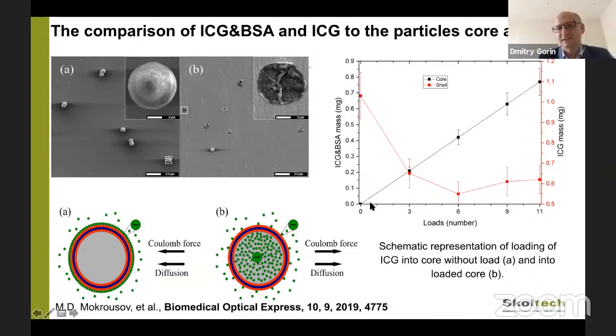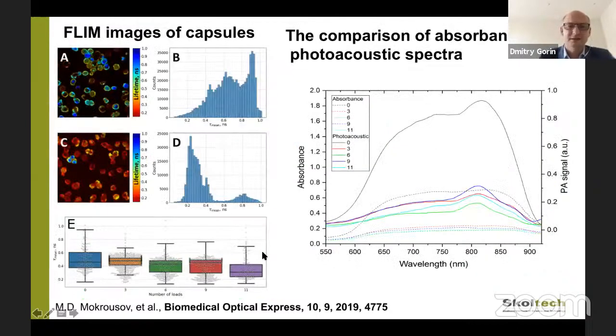It looks like this. If we don't have any preloading, conjugate albumin with indocyanine, we have the highest adsorption of this in the shell. And here you can see that we can calculate the amount of ICG in the shell and the amount of ICG encapsulated into the capsules. And here you can see that we have real self-quenching.